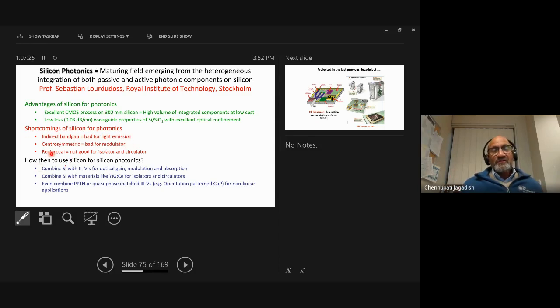Because of the reciprocal nature of the semiconductor, you cannot create isolators and circulators, so you cannot decouple the ingoing light and outgoing light. That's where people are trying to combine silicon with III-V semiconductors with optical gain, modulation and absorption, and also combine silicon with materials like yttrium iron garnet, magneto-optic materials, for isolators and circulators. People are also trying to combine lithium niobate, periodically poled lithium niobate, and quasi-phase matched III-V semiconductors like gallium phosphide for nonlinear optics applications as well.